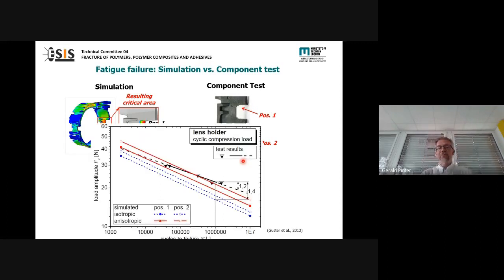If you then compare simulation with the component tests in this diagram, you can see the triangles. These are the outcomes of the component tests. And in red and blue, you see the simulation. In red, this is the simulation where the anisotropic behavior is considered. So here, the fiber orientation is considered in the calculation, and in blue, it's an isotropic calculation without considering the real fiber orientation. You see that if you compare the red curve with the triangles, there's quite a good match between component behavior and simulation.